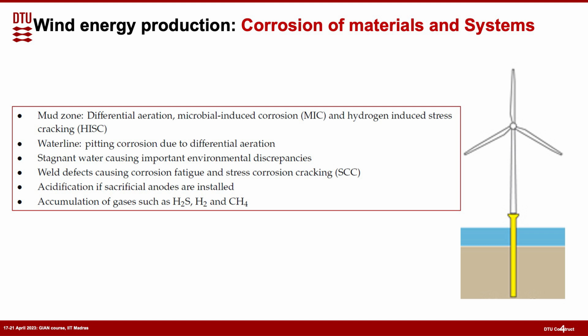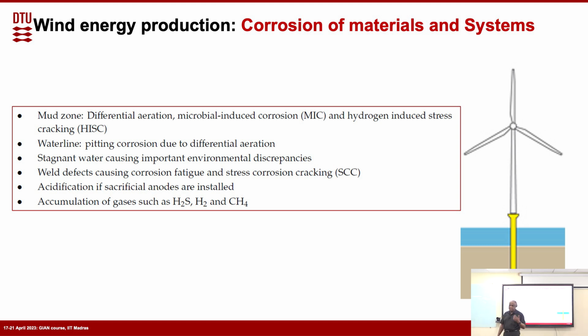And if you look at it, there is a lot of fatigue loading here, right? Because when this is rotating, although we don't see it, there is a lot of vibration for the tower. And because of the wind in the sea, this is actually flexing a little bit. So there is a lot of fatigue loading here. That means that if the hydrogen is going in, then you can have hydrogen embrittlement, which is assisting the fatigue failure. So the mud zone also has a problem. But the only thing is that from the corrosion point of view, maybe more issues are here rather than here, because this is inside the mud, and that way the corrosion is less, but because of the splash zone, there is much more corrosion in this area.